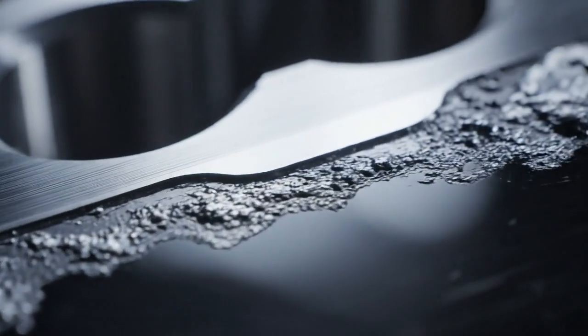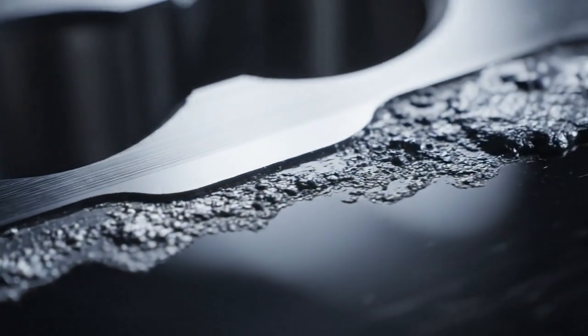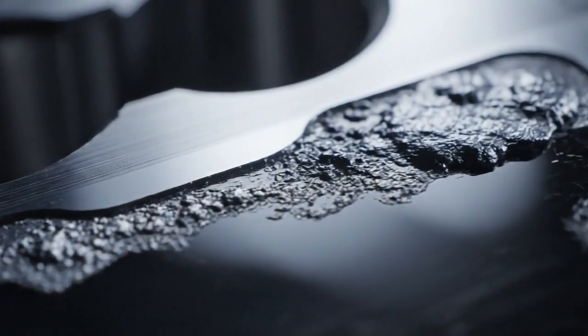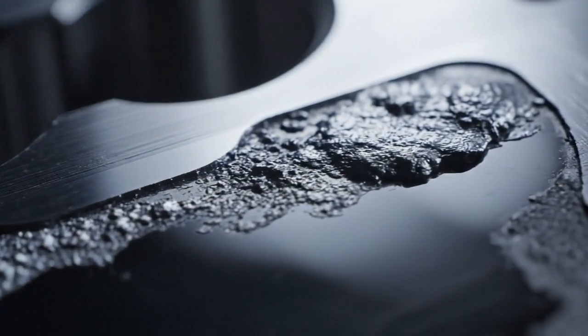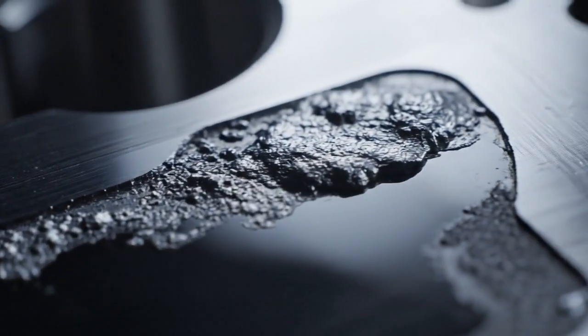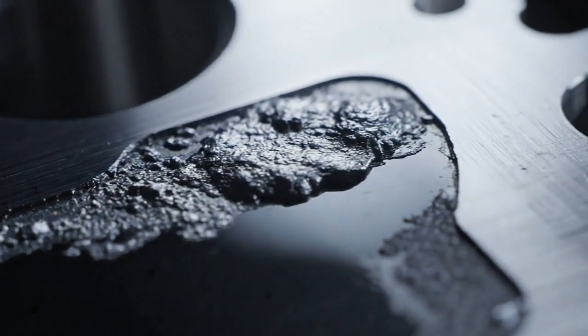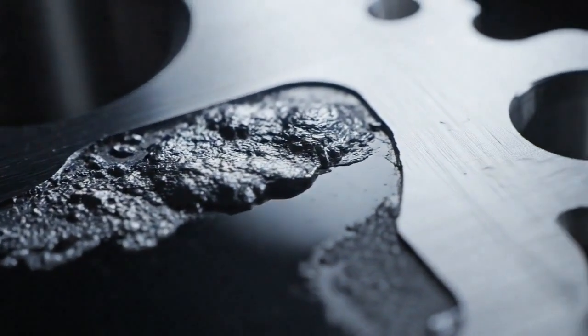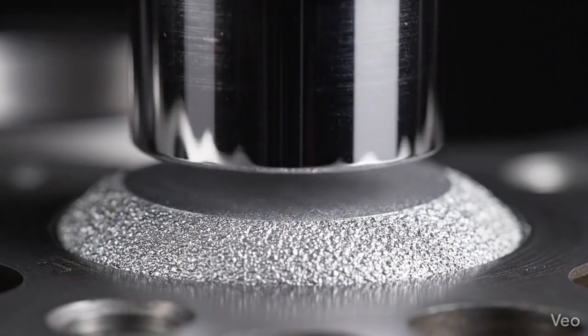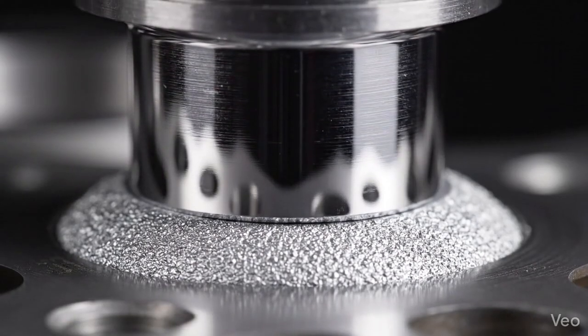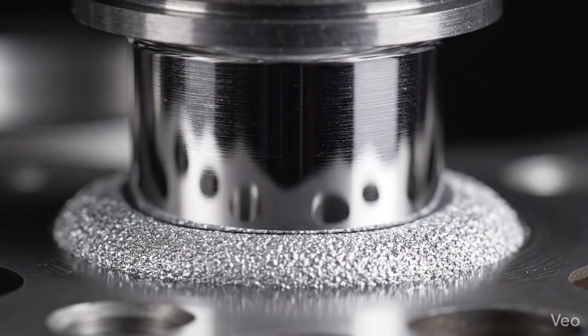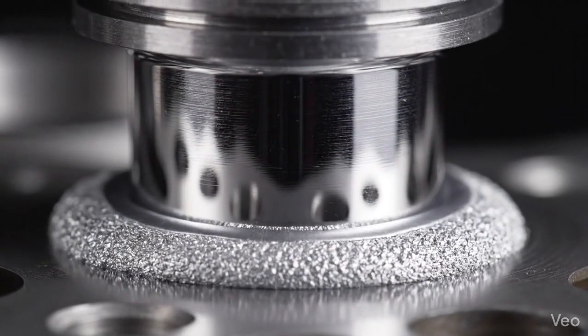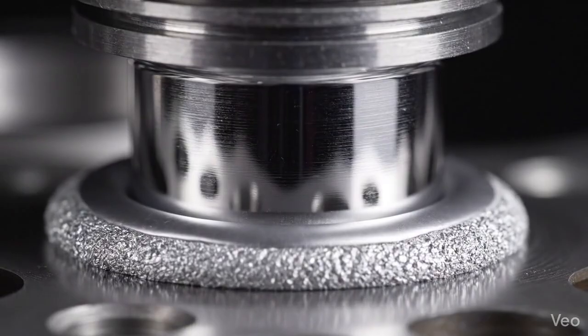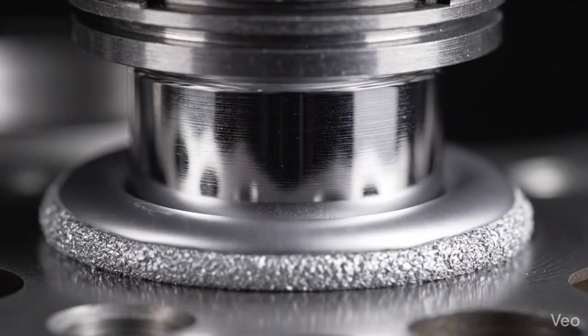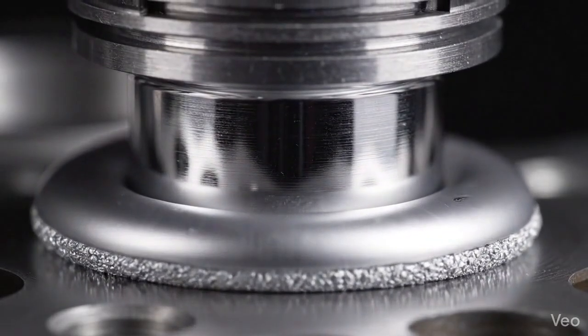Tetraethyl lead, the octane-boosting additive blended into gasoline since the early 1920s, deposited a thin, soft layer of lead compounds on the valve seat surface during every combustion cycle. This lead film acted as both a lubricant and a cushion. The exhaust valve was not striking bare iron with each closure. It was striking a surface that was continuously renewed with a microscopic layer of soft lead deposit.